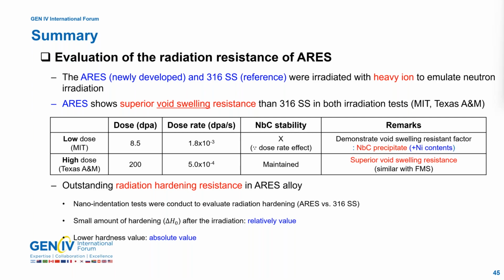The primary mechanism of the inhibition of the void swelling is the dynamic evolution of radiation-induced defects along the precipitate-matrix interface at elevated temperature. In addition, the degree of irradiation hardening measured by nano-indentation was much smaller, which can be correlated with fewer radiation-induced defects for ARES than 316 stainless steel. Both significantly less void swelling and less irradiation hardening indicate the superior irradiation resistance of ARES for the application of the next generation nuclear system.